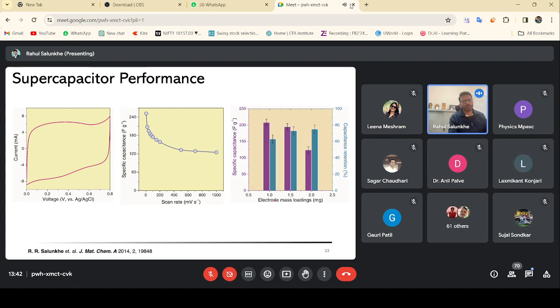We have varied the electrode mass loading, and we can see that the capacitance retention goes on increasing as we increase the mass loading, but the capacity is slightly less because the accessible surface area to the electrolyte ions is a little bit lower, and because of that the capacity starts degrading.